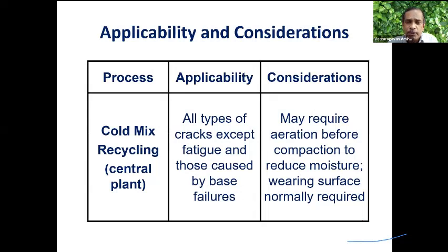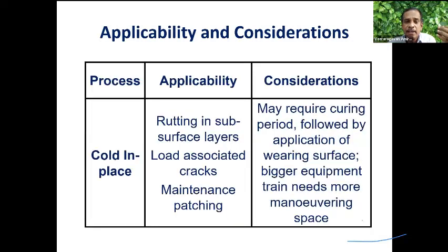It's possible you can go in for environmentally friendly cold mix. Again, it can be done as central mix. Wherever the lower layers are deteriorated, I can mill the entire material. I can add a virgin mix. I can add an emulsion or a foam bitumen and then use it again. I can also do cold in-place recycling. In a central plant, I mill the material, add virgin binder, recycle, and lay it back. I'll show you in a video clipping.